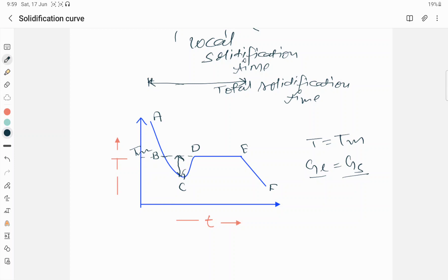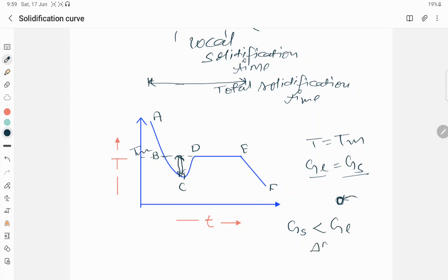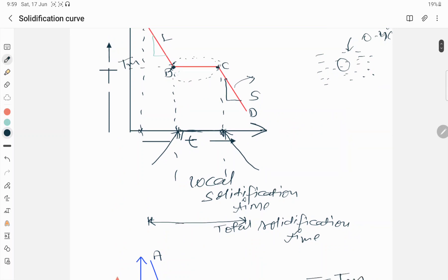To supply some energy for surface creation — in most cases the nuclei which form are spherical in shape — there is some surface associated with these nuclei, and that surface is associated with some surface energy which you have to supply. So to supply that surface energy for the creation of nuclei, you have to undercool the liquid. When you undercool the liquid, the Gibbs free energy of solid will be less than the Gibbs free energy of liquid, and that change in free energy, delta G, is the energy released and supplied for surface energy creation. That's why there is undercooling.